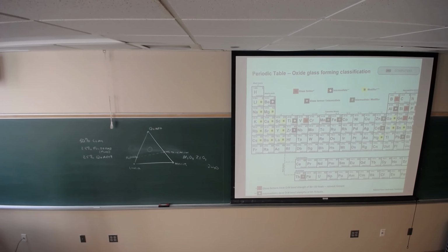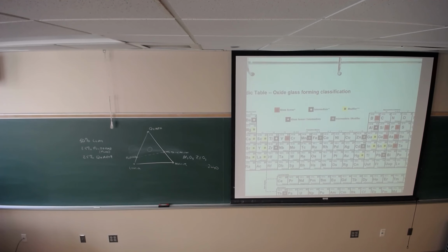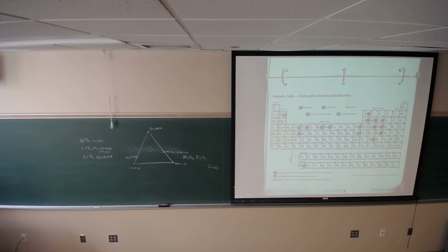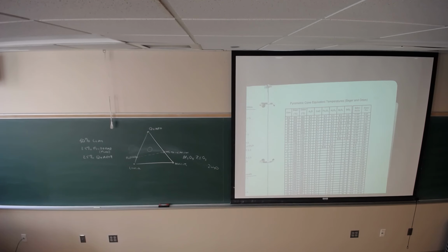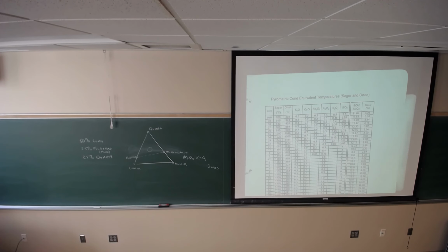And then you have the glass formers, which are the red with the red square with the black dot in the middle, like silica and phosphorus, which we don't care so much about, antimony. And then you have the intermediates, like alumina, for example, and then there's some that are sort of in between that, like glass forming intermediate, etc. So this helps you see glass formation. And then when we flip to here, there's Pauling's rules for silicate, and then here's your pyrometric cone chart. Okay, so you get an idea. This is a big deal.